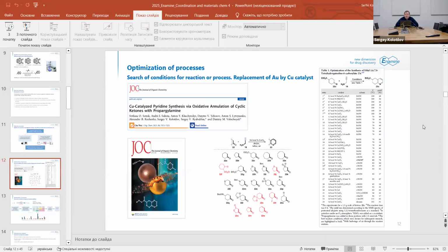We have good experience in optimization of processes. For example, on the slide, you can see the results of optimization of synthesis of fused pyridines from cyclic ketones and propargylamine. This reaction is known, so we were not the ones who found this reaction, but it could be performed on gold-containing catalysts. And it was very good, it was stable, but the problem is that gold is expensive. So we tested different copper-containing systems and different conditions, and we found conditions to carry out this reaction on a multi-gram scale, in some dozens of grams.